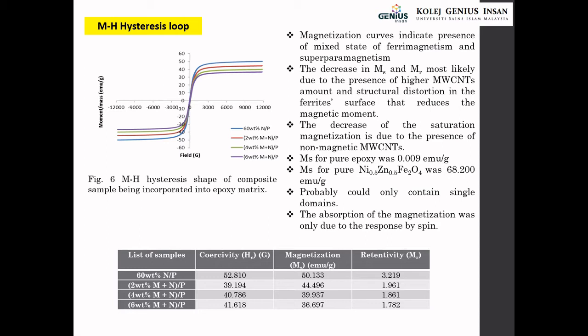From this research we have found that the pure epoxy was 0.009 EMU per gram, and MS for pure nickel zinc ferrite is 68.2. So it probably could only contain a single domain in the sample, and the absorption of the magnetization was only due to the response by spin.